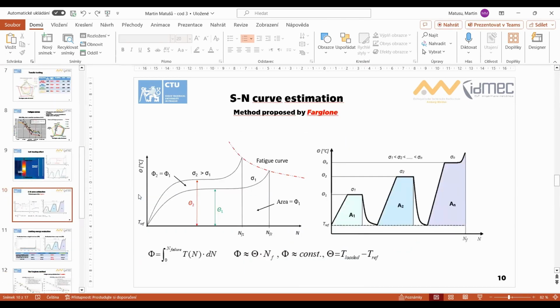So the SN curve estimation was based on the method proposed by Fargione, which says that there is a material parameter called limiting energy, which is valid for all the testing specimens. It's invariable on the amplitude of load, and it's the area under the temperature evolution, as you can see here. We'll try to examine if this is true. I will show you in the second slide here. And also we will try to do that.